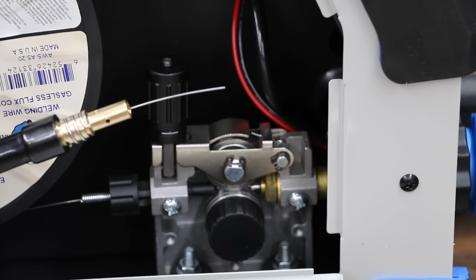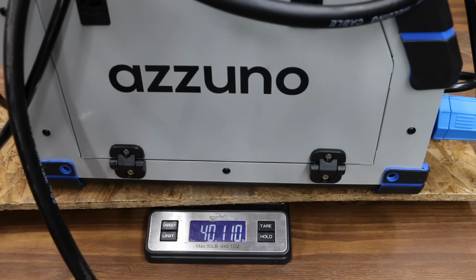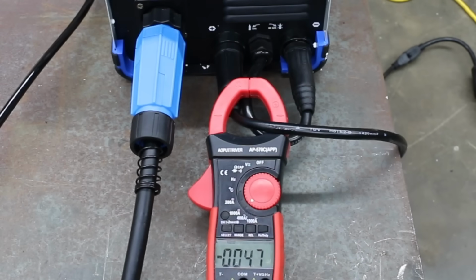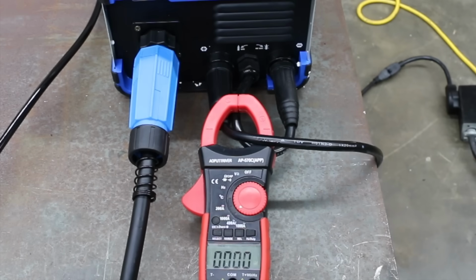And the Azzuno with 10 pounds of welding wire on board weighs very close to 40 pounds. On the lowest setting, starting off at 22 amps and warming up into the 40s. On the highest setting, starting off at 206 amps and cooling down to 196 at 3 seconds.